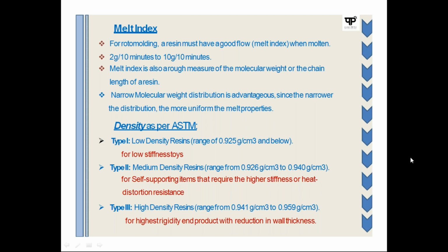So here in this case, the material property I'm going to stress is the MFI. Depending on the product shape and the size of the product, you can select the MFI, but the range which is normally preferred in most cases is 2 grams per 10 minutes to 10 grams per 10 minutes. So this particular range, you can select according to the shape and the material which you're going to use.